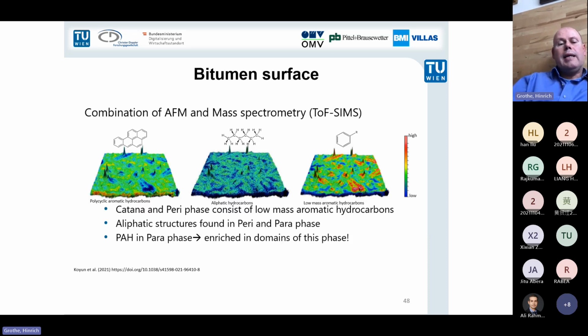So we applied then a correlation of atomic force microscopy and mass spectroscopy. It's time of flight mass spectrometer in the SIMS mode, and you can really recognize here different molecules which have been analyzed, and then this information has been correlated with the AFM picture. And you see that the chemistry is really different on different spots.